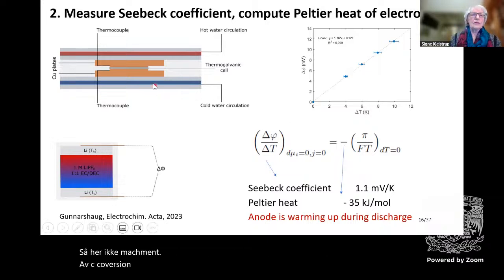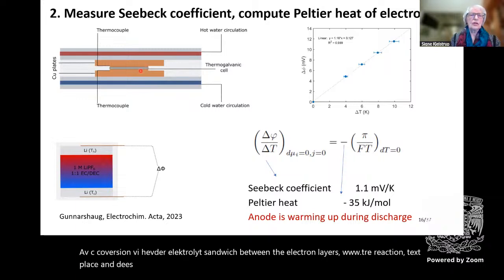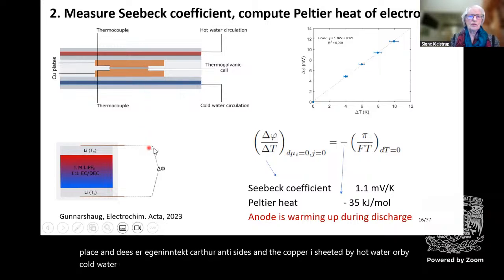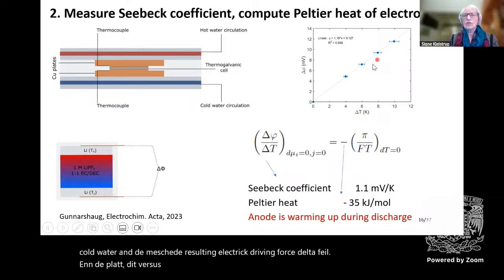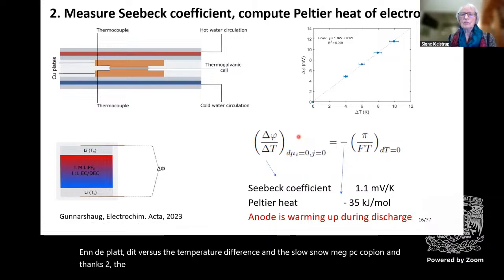We have the electrolyte sandwiched between 2 electrode layers where the reaction takes place. And these are again in contact with copper on 2 sides, and the copper is heated by hot water or by cold water, and we measure the resulting electric driving force, delta phi, and we plot it versus the temperature difference, and the slope is now my Seebeck coefficient, and thanks to the wonderful symmetry of the Onsager matrix, we find the Peltier heat from this identity.